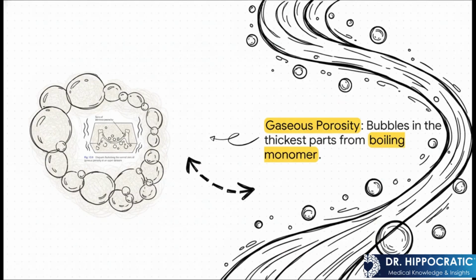And this picture shows you exactly what happens. That boiling monomer creates bubbles, leading to our third major defect, gaseous porosity. These voids usually pop up in the thickest parts of the denture, where it's hardest for all that heat to escape. And as you can imagine, this severely compromises the strength of the final product.